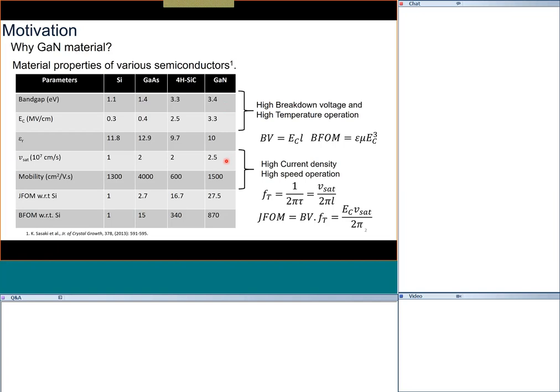Another major feature making gallium nitride attractive for RF applications is saturation velocity. We often talk about mobility in textbooks, but because we are greedy for higher speed and apply such high voltages, electrons already move at the highest velocity possible in the semiconductor — that is the saturation velocity. Even if you increase the voltage or electric field further, the electron velocity will not increase beyond that saturation velocity.